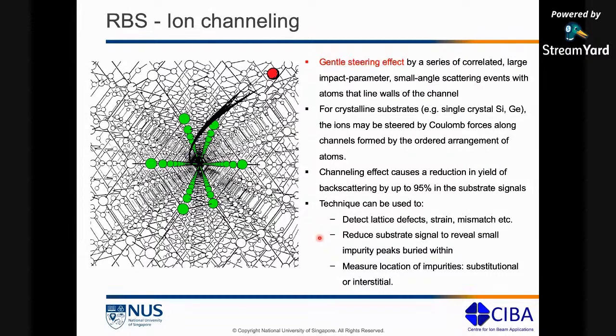So RBS, or rather ion channeling in layman's terms, right? So when you have an RBS setup, what happens? You have an incident alpha particle coming in towards your sample at a very high energy. When it collides with the sample, some of those particles will backscatter, and depending on what element you have in your sample, there will be a specific backscattered energy for the backscattered helium particle. If you're able to detect that energy, that will tell us what element we have in your sample. So if you have gold, your backscattered energy will be very high. If you have silicon, your backscattered energy will be lower. So we can calibrate this and identify which element we have in your sample. That is, in layman's terms, what RBS means.